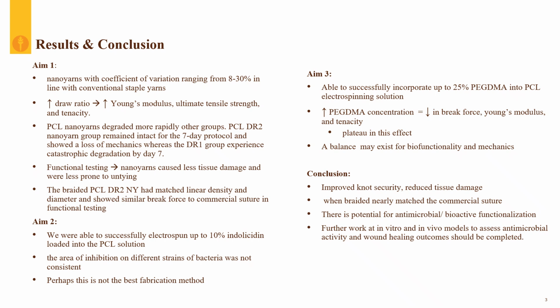So going through our results and conclusions for aim 1, looking at the performance, the nanoyarns were fabricated with a coefficient of variation ranging from 8 to 30%, which is in line with a lot of conventional staple yarns. As we increased our draw ratio, particularly for the PCL group, we increased Young's modulus, ultimate tensile strength, and tenacity. The PCL nanoyarns degraded more rapidly than the other groups.